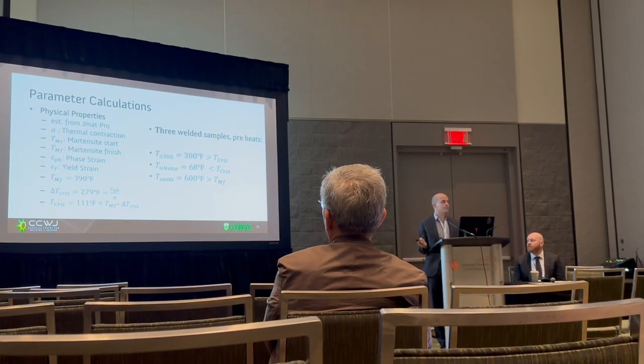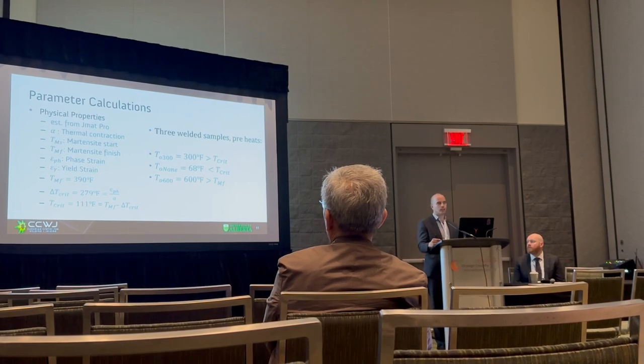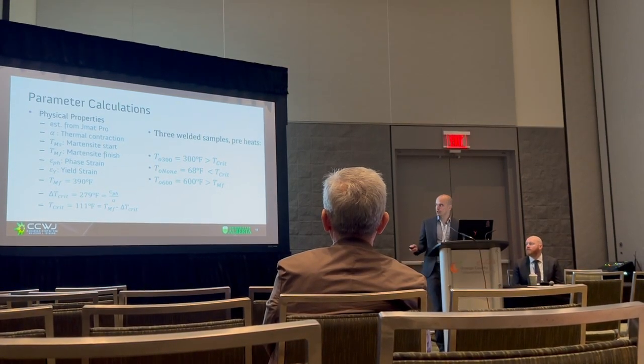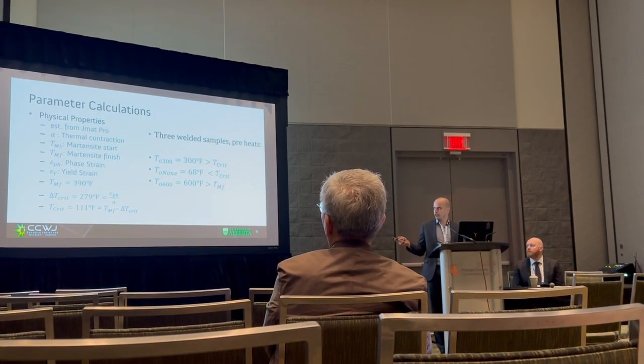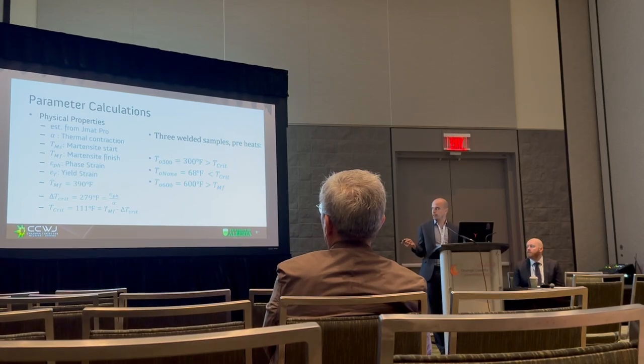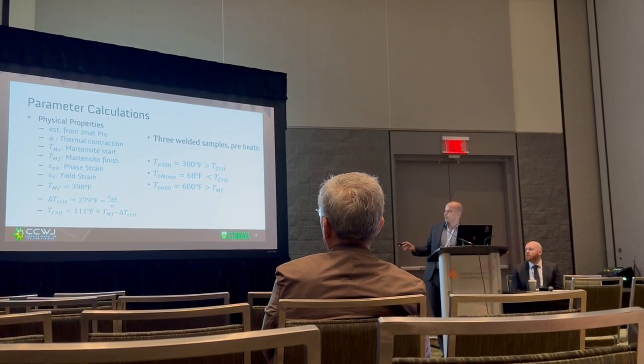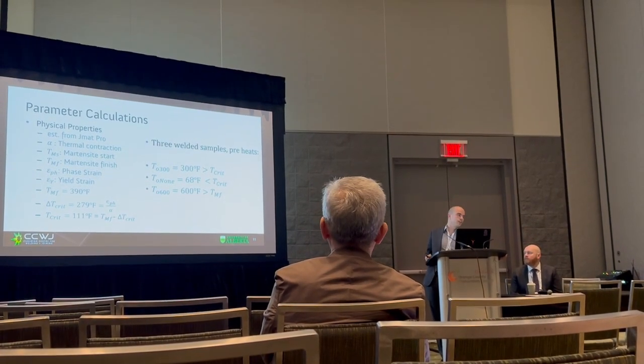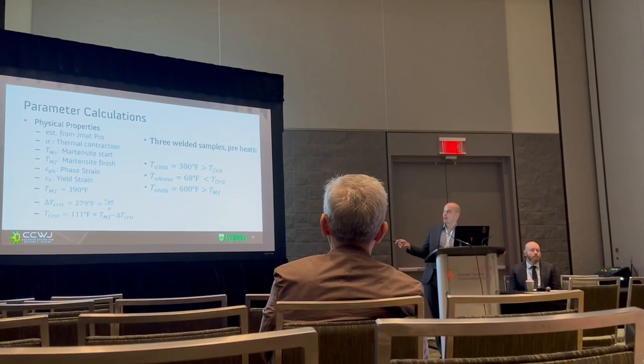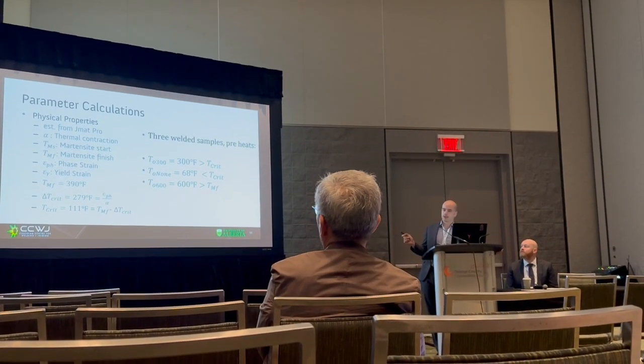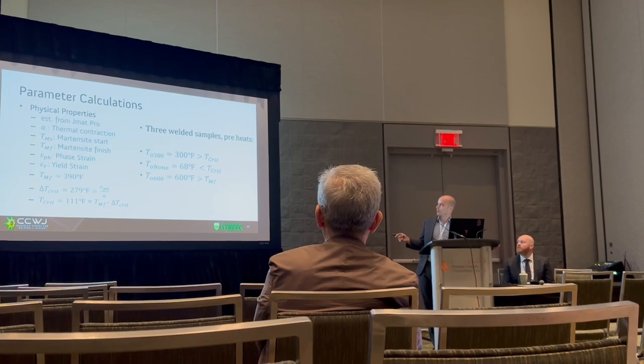So I have 279 degrees Fahrenheit of cooling that I'm allowed to use between reaching the martensite transition completion and equilibrium temperature. So we look at our preheats. That gets me 111 degrees Fahrenheit. So if my equilibrium temperature is higher than 111 degrees Fahrenheit, I'm going to get some benefit from that phase transition. So we've got three cases.